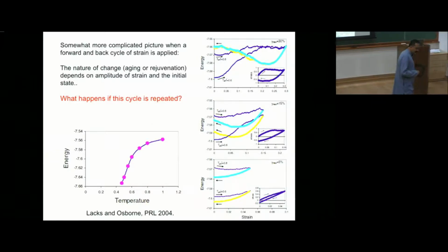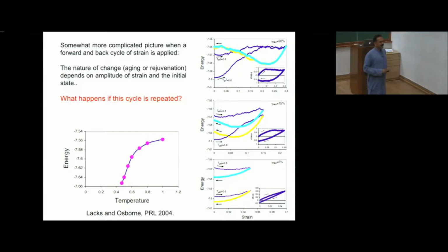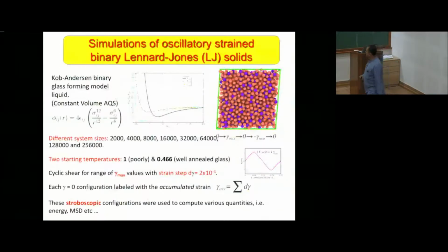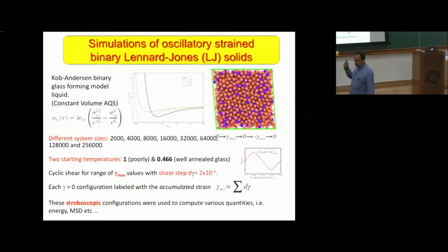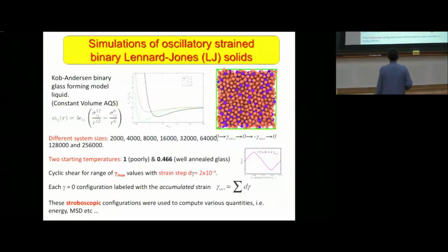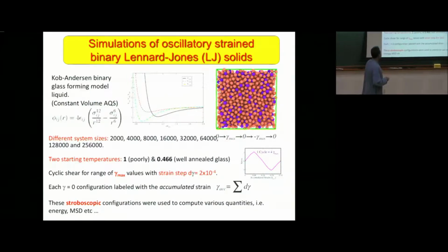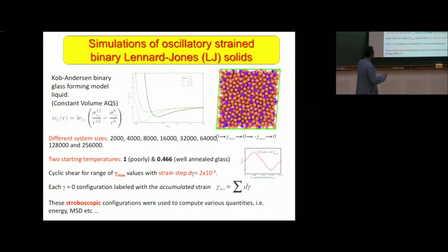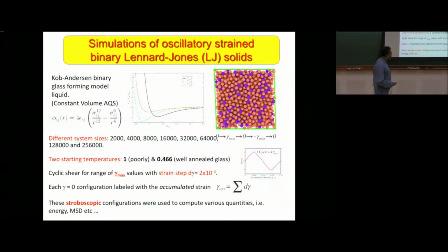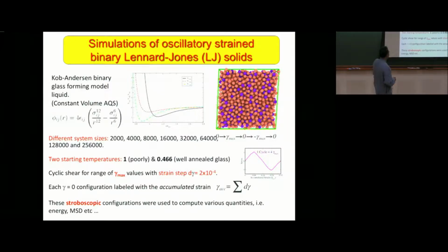So our starting point was to say, what happens if I do this again and again and again, right? That's how we got into doing cyclic deformation, because this is clearly showing that there are interesting annealing effects when you deform. So this is what we do for a model glass, which is called the Kob-Andersen mixture, and we do this for a whole range of sizes, and the reason for that I'll mention in a minute.